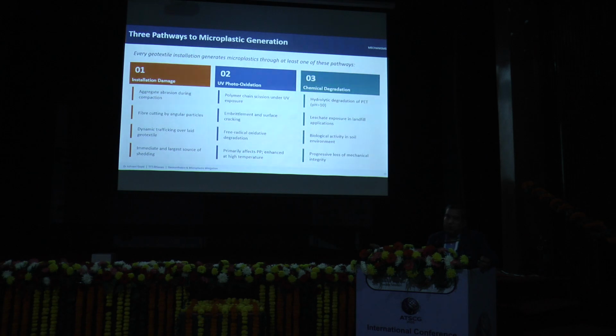If we talk about polyester materials, there the issue is hydrolytic degradation. If the polyester material faces alkaline media greater than pH 10, then oxidation happens, the polyester bonding breaks down, and the tensile strength reduces day by day. That starts the leaching of microplastic from the surface of the polyester material. So these are the ways microplastics are released during usage.